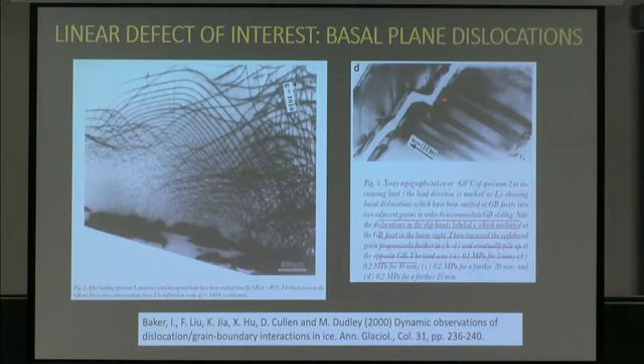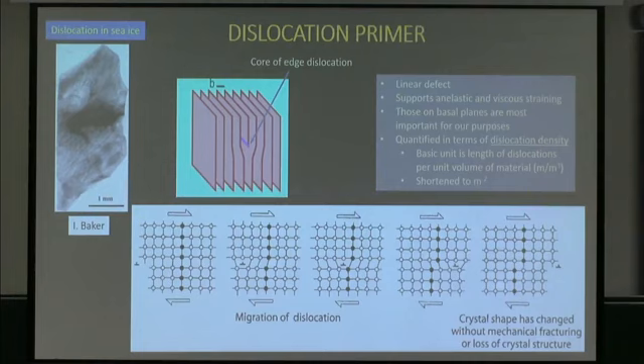The other thing that's noteworthy and has been important in terms of understanding polycrystalline behavior is that grain boundaries in ice are not nice and smooth. They have ledges. These ledges, once it's under stress, are very prolific sources of dislocations. So there's no problem in producing dislocations in ice. Sea ice, as you can see, the guys have looked at it and they go, there's just too many, we can't even count. Just be satisfied that it's completely loaded with dislocations even before deformation takes place.